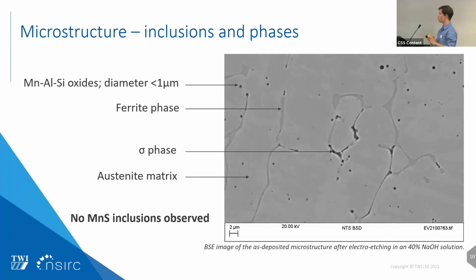Those inclusions are found to be well embedded within the matrix, and after investigation, they didn't seem to be relevant or affecting the corrosion properties. Also interesting is the fact that we don't have any manganese sulfide inclusion within the microstructure. We couldn't find any, and they seem to be replaced by those small oxides instead. This is probably due to the high cooling gradients during the deposition, which doesn't allow time for those manganese sulfide inclusions to form.